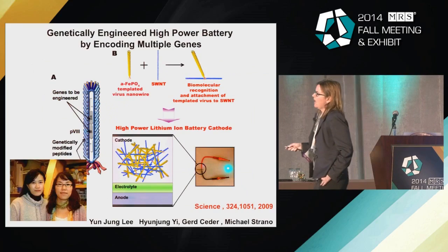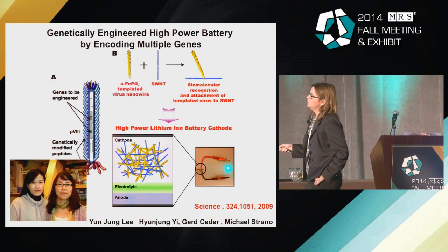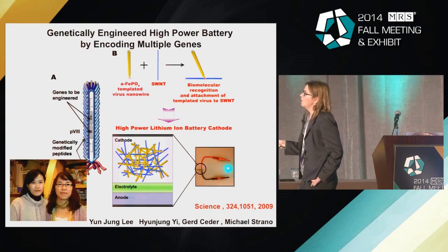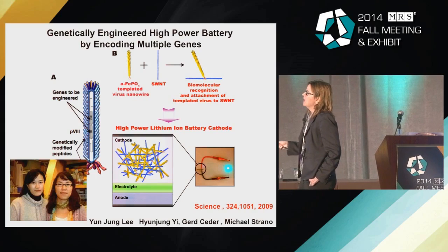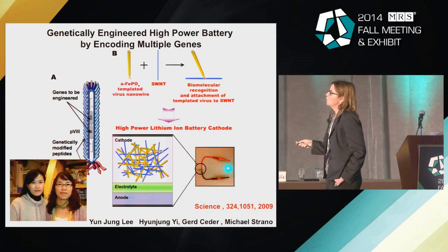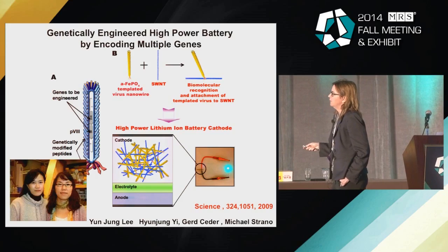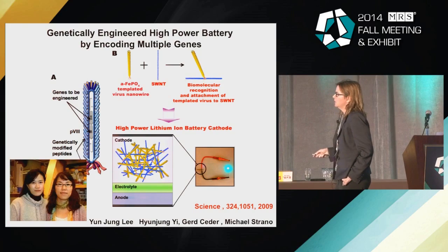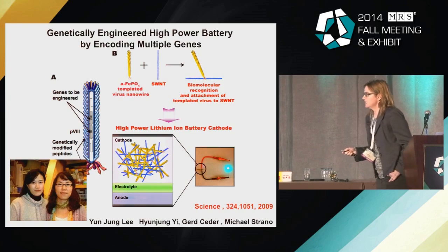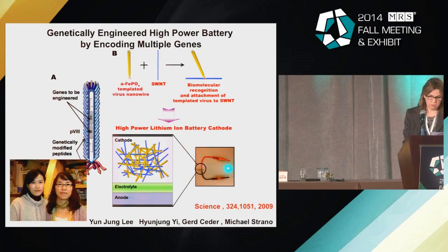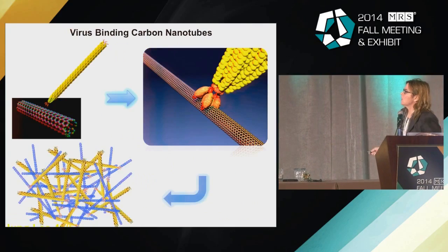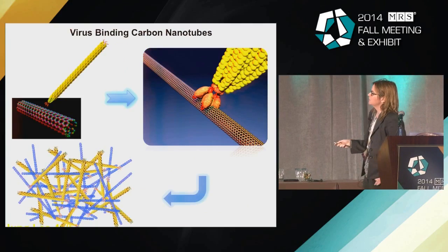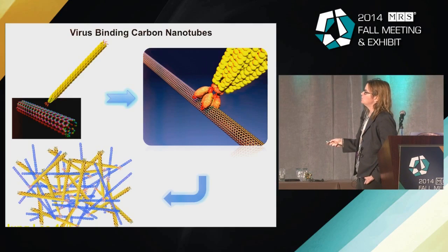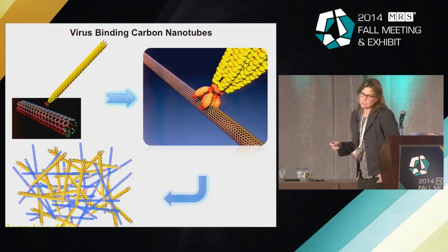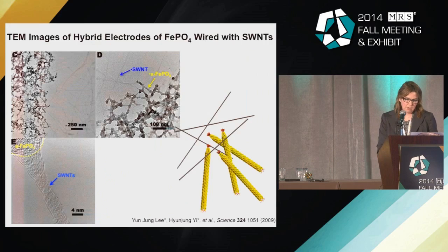So we decided to look at cathode materials, and what we decided to do was take a virus to see if we could get it to bind a single-walled carbon nanotube on its tip, and then simultaneously have the ability to grow an iron phosphate material, and then wire itself to the current collector. These were two very talented students, Yoongjung and Hyungjung, in my group. And they were able to accomplish that. They were able to select viruses that could bind single-walled carbon nanotubes on the tip and then have a different sequence that could nucleate iron phosphate material along the edge.